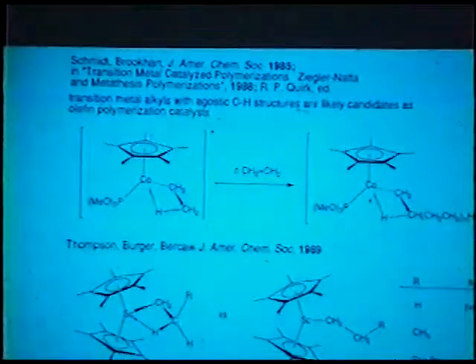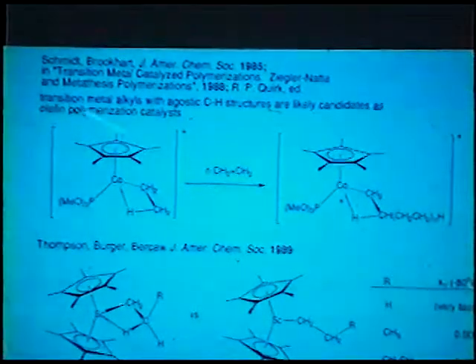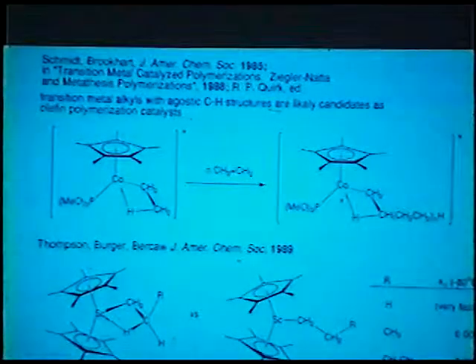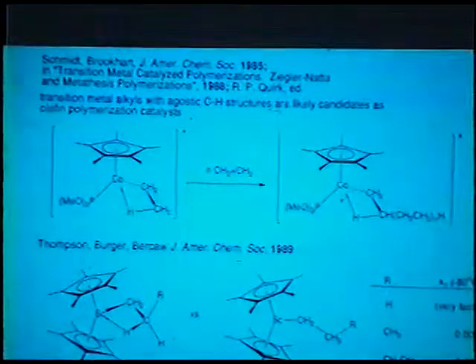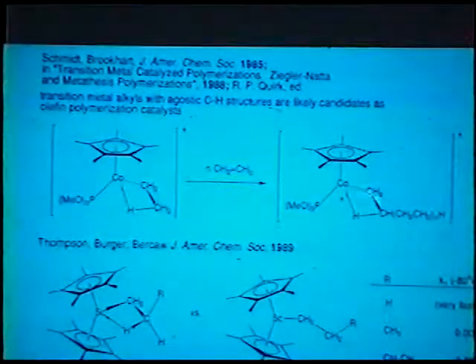Brookhart went further and pointed out that these systems, when you have agostic interactions, especially the beta-agostic interaction, are likely candidates for olefin polymerization catalysts. So he made some very reasonable arguments about when one might expect olefin insertion to be favored, and in fact, although there are a large number of olefin hydrides that do not do olefin polymerization, those that have agostic interactions are now found commonly to affect olefin polymerization. In this case, he actually went to the lab and found a system and showed that ethylene insertion proceeds with this particular ethyl complex.